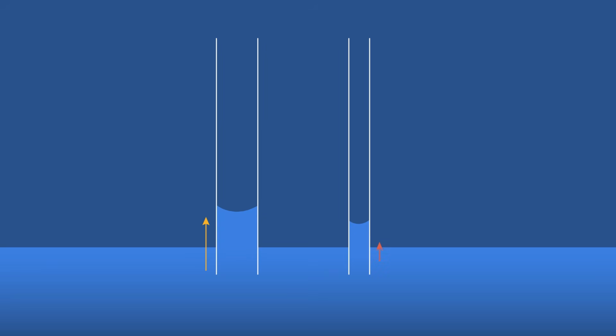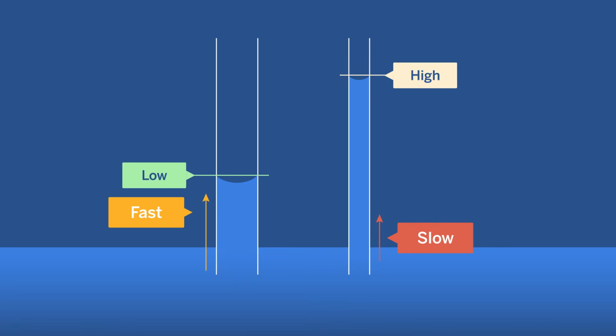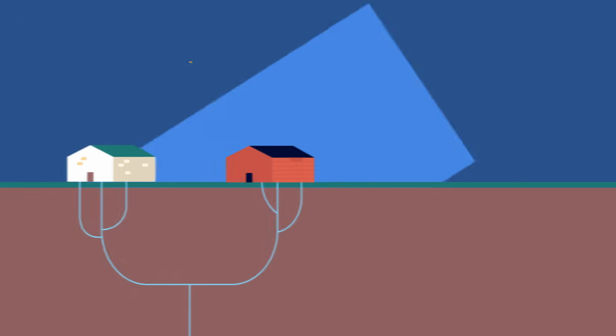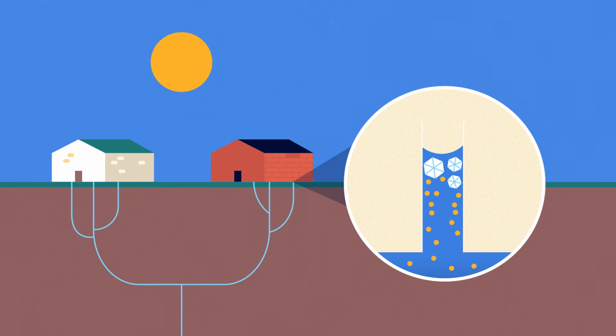In previous videos, we described how capillary rise depends on the pore size and contact angle, among other parameters. We saw that the rate of rise increases with pore size, but that the maximum height of this rise is inversely proportional to the pore size. In most practical situations, we must additionally consider the role of evaporation during capillary rise.